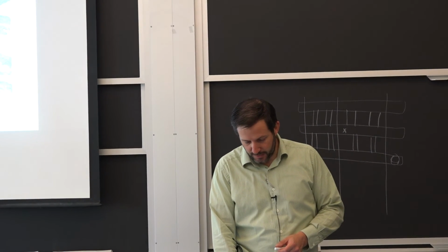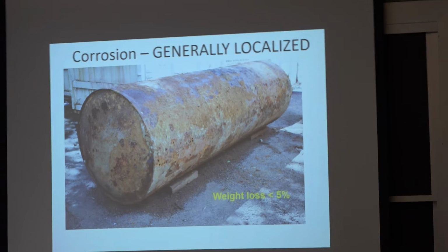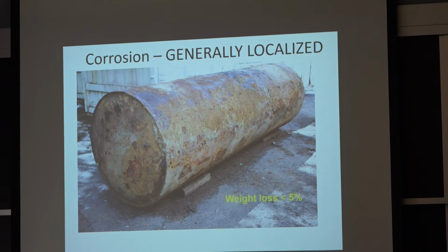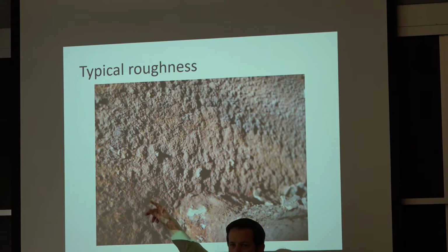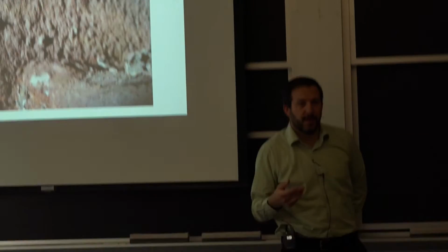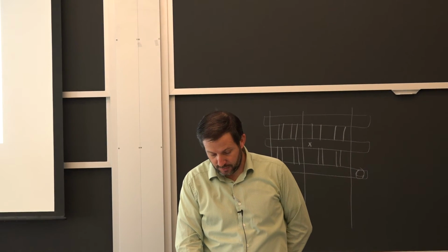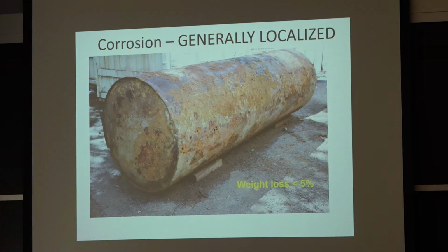What happens when you have corrosion over time is a little bit more complex. So this is a tank that was in the ground for 60, 70 years. So when we're talking about the surface of the tank right here, it's rough. It really was all exposed to the same environment. So if you measure the thickness at these different locations, it is still very similar. And the main reason is it's the same environment. You transfer from anode to cathode all the time, and then eventually you just lose thickness in a relatively homogeneous manner, and that's what happens a lot in atmospheric corrosion.